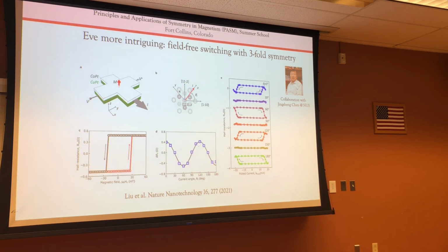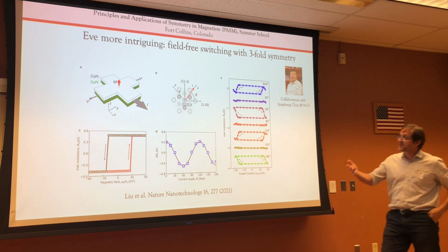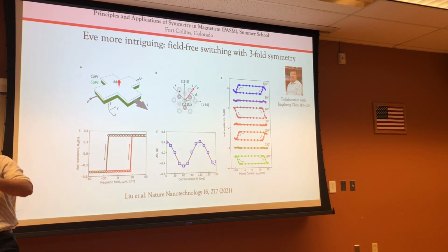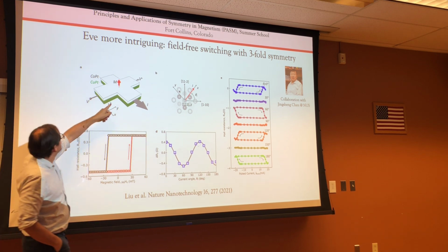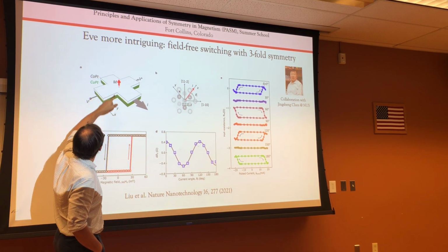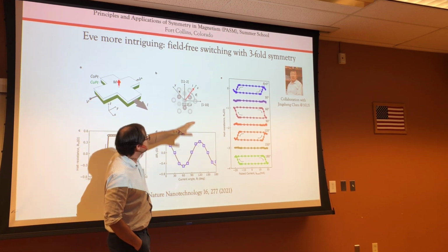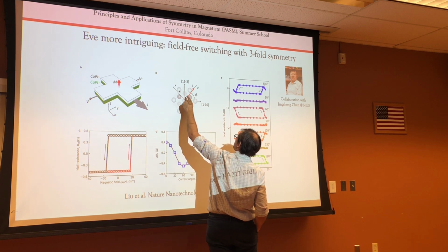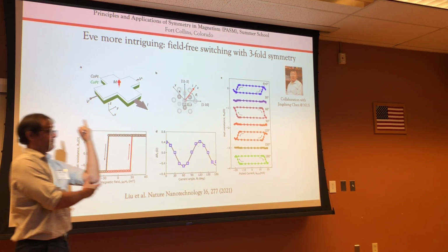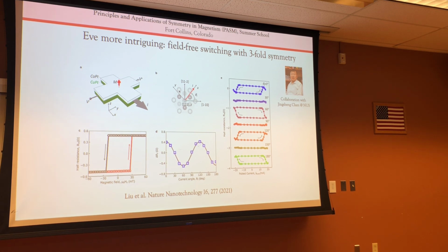And indeed, he measured the current-driven switching. He has this cross where you have your cobalt platinum. Because of the strong spin-orbit coupling, the magnetization is perpendicular. So you send the current through the cross, and what he gets is that without external field, depending on the relative direction between the current and the crystallographic axis, it can get field-free switching. So it brings the magnetization in plane, and something happens that completes the reversal.